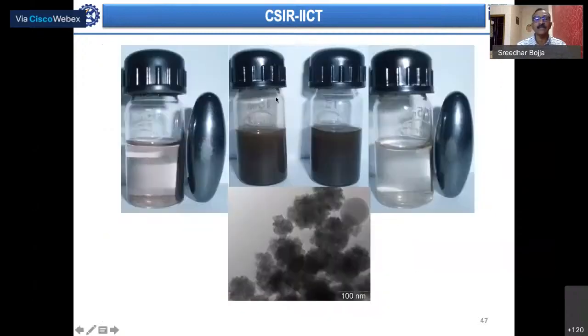As you can see here, they are in two different solvents, and by just placing a magnet you can separate them from the reaction mixture. This is the silica sphere on which these iron oxide nanoparticles are coated. Some people coat it on the surface, some encapsulate iron particles into the silica spheres. Depending on whatever way you want, you can synthesize such kinds of morphologies and do it.